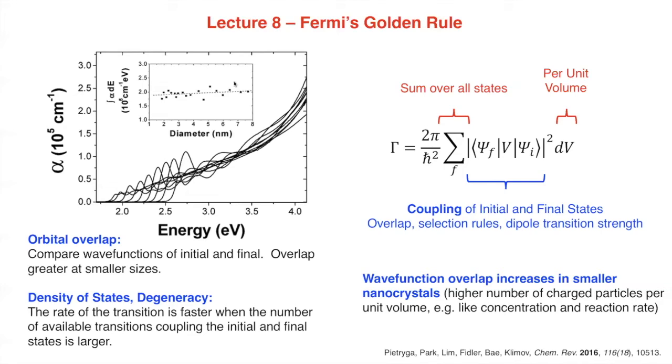And as you go to lower and lower energies and you start getting into these excitonic states, and particularly the lowest energy excitonic transition, which is this bump that you see here, the intensity of that bump changes as a function of the size of the particle. So we're going to lower energies down here. So these spectra are for larger particles. This spectrum here is for the smallest particle in this series.